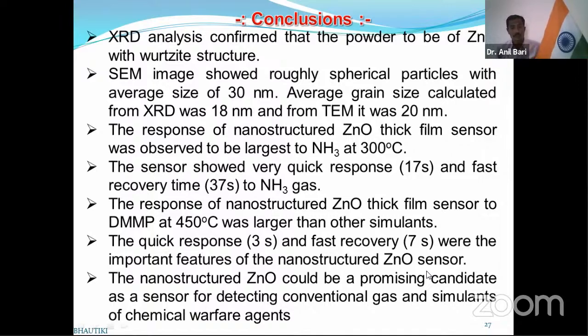The response of nanostructured thick film sensors to DMMP at 450 degrees centigrade was larger than other simulants, while the quick response of 3 seconds and fast recovery of 7 seconds were the important features of the nanostructured sensors.